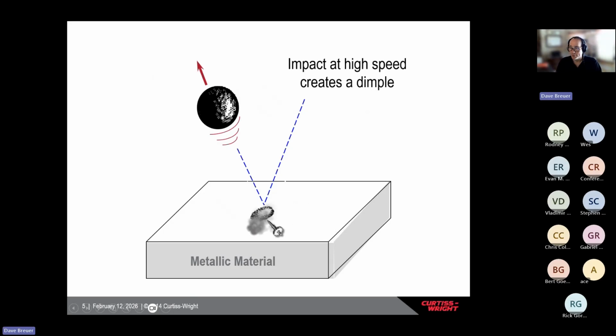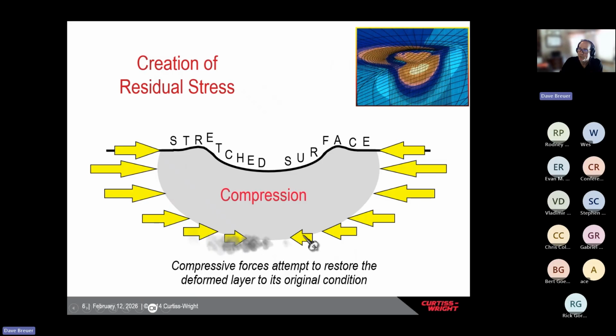So when we look at this dimple, on a more technical basis, this is actually a zone of residual compressive stress. Remember, this residual stress is in the part with no external loads. When the BB or shot media strikes the surface at the point of impact, it physically elongates and stretches this impacted area to the point where it yields in tension, and then the media bounces off the surface. The surface then tries to restore itself, trying to push that dimple out, and in that attempt to restore itself, it leaves the surface in residual compression.